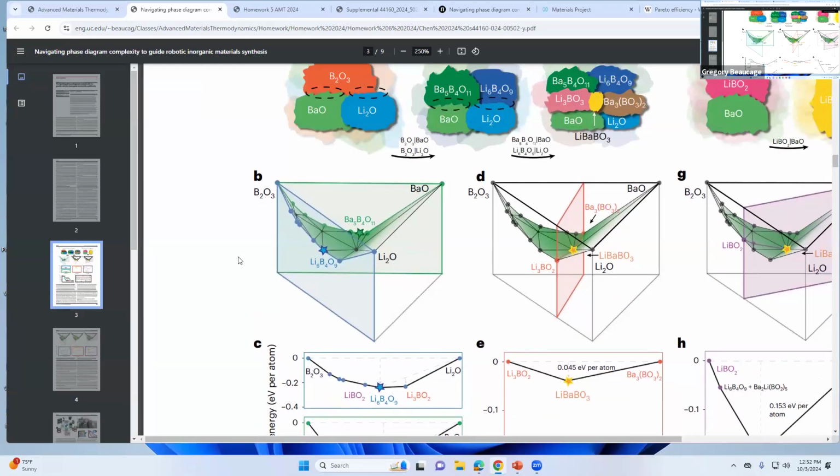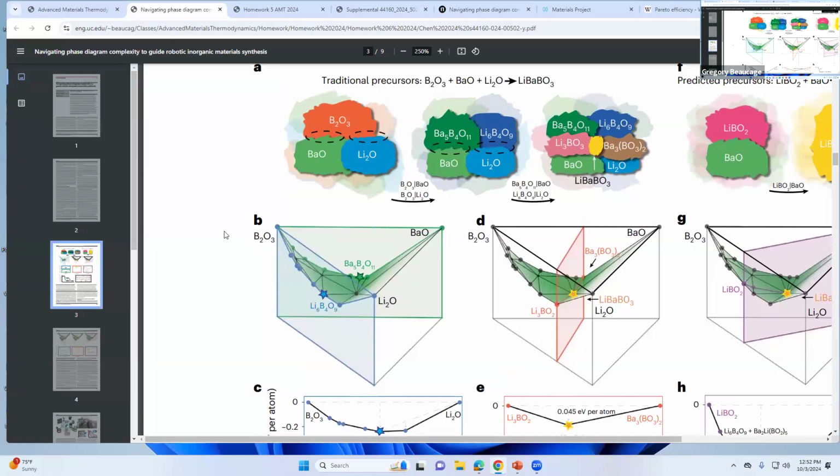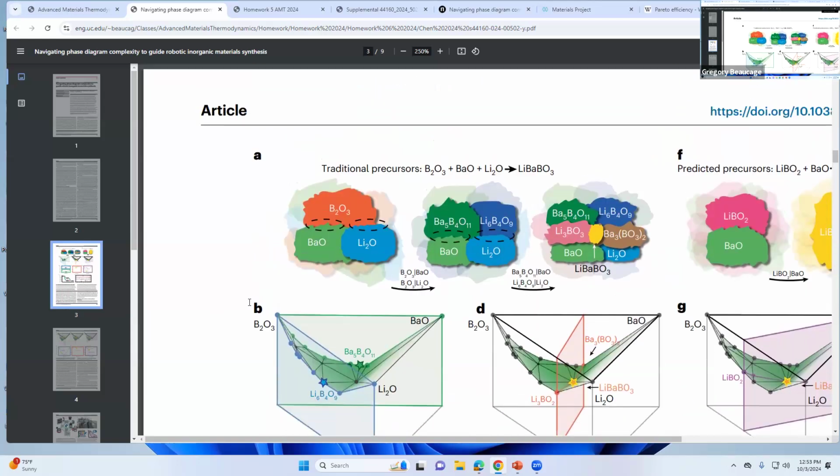So all these things are ignoring the entropy. The DFT doesn't give you entropy. In the free energy, which is really governing it, it's going to be the enthalpy minus T delta S. Right. So without the entropy, you're kind of missing something. So all these things will say, like, oh, we can ignore entropy for whatever reason, like just ad hoc. Right. So that's a little bit of a flaw, but they do talk about it in the paper, or they mention it.